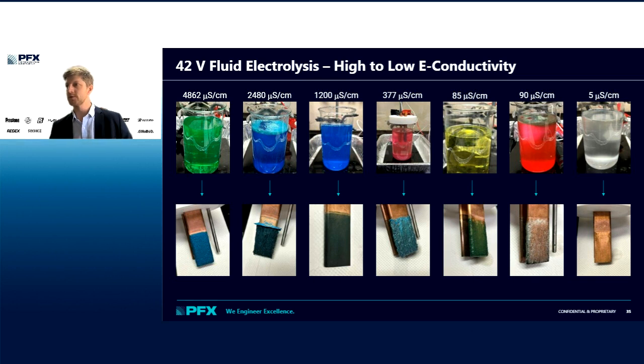So there are some trends here that might not be universally true, but generally the higher electrical conductivity fluids lead to a higher amount of deposits on the electrodes at the end of test. Specifically, as we move to the low conductivity, right, you can see our fuel cell coolant at 5 microsiemens, essentially no reaction with the current. There's no buildup. And then as we move to the left with some of these higher electrical conductivities, we have a significant amount of deposits. This is 42 volt testing.